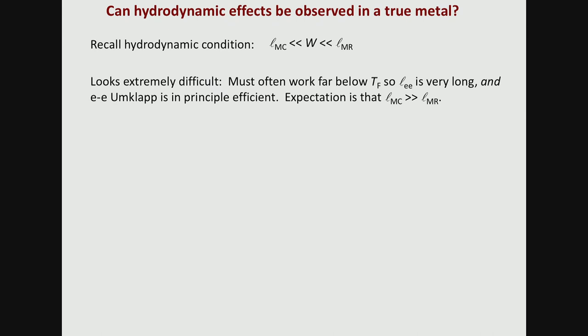Even if you could somehow find a way of getting that electron-electron mean free path to be shorter by cranking up the electron-electron scattering, if your Fermi surface is big, then the umklapp processes for electron-electron that I told you about will come in and spoil that as well. So there's lots of reasons to not want to trust electron-electron scattering to do what you want here. And the expectation in a standard metal is that you'll always be stuck with the momentum-conserving mean free path being much longer than the momentum-relaxing one. In other words, standard metals, you would think, would always be stuck in the ohmic regime.